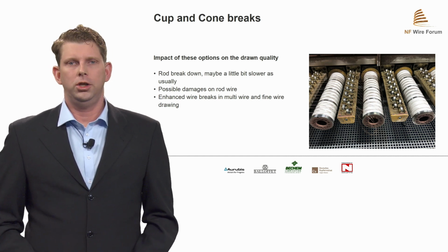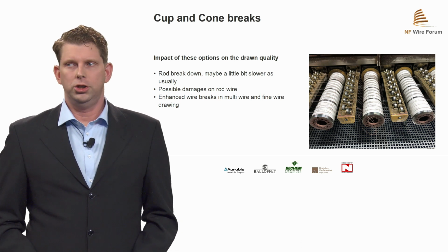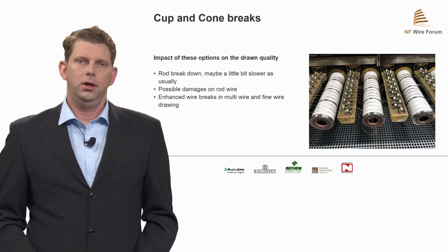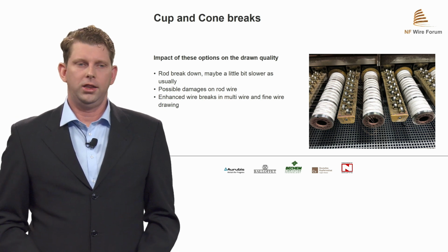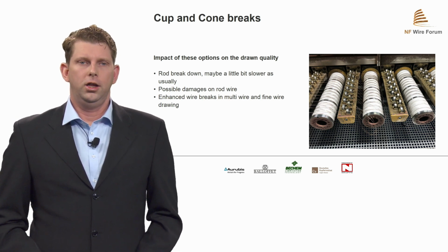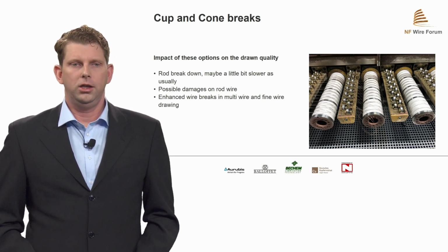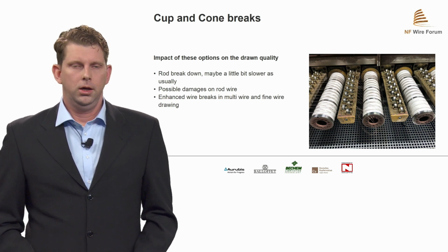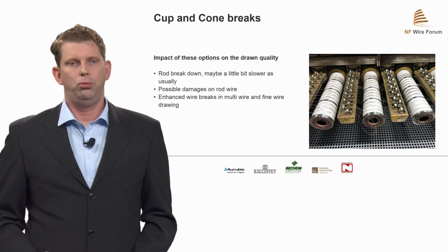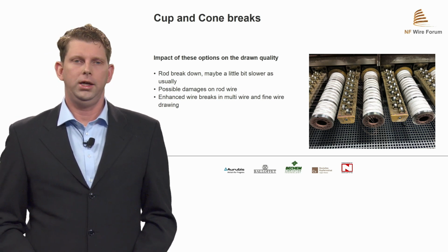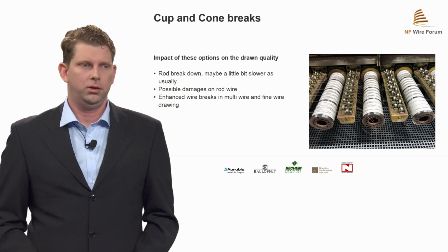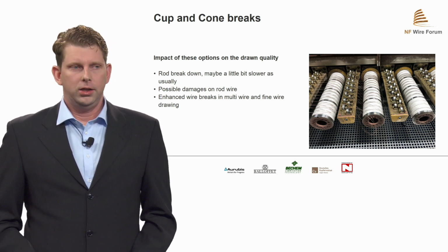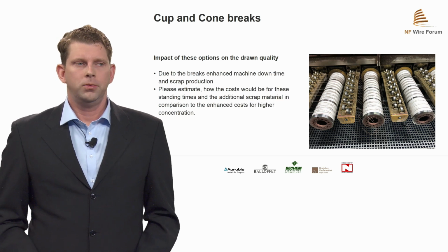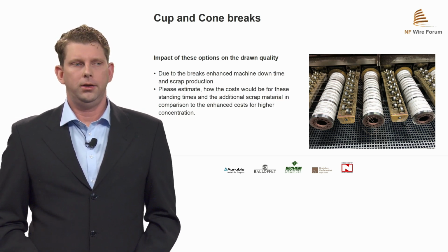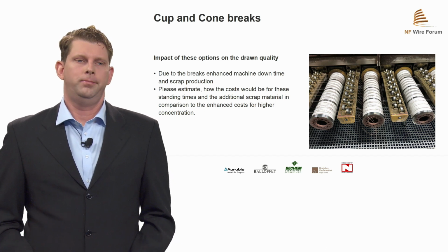Secondly, you get small damages to your rod wire. These small damages stay the same size while the diameter gets lower. So the damage area gets bigger in relation to the total diameter, and by this a break can occur over the time. So this is where you can see that the pre-damaging in the rod breakdown can cause breaks in the multi-wire or even in the finest wire steps. This enhanced breaks in the multi-wire and fine drawing section will cause machine downtime and scrap production.